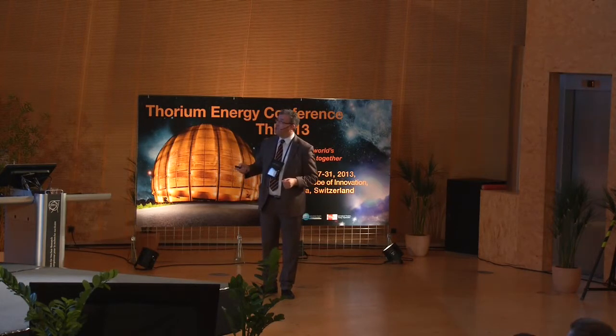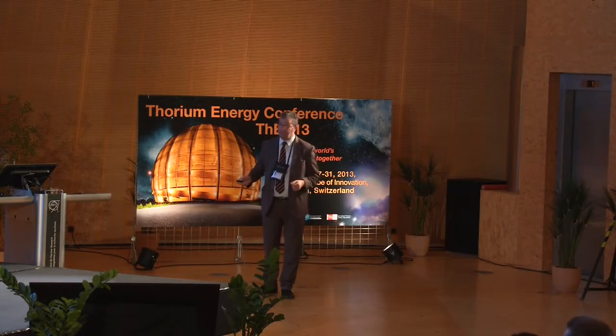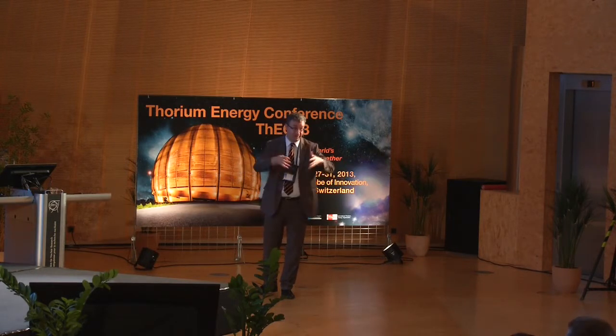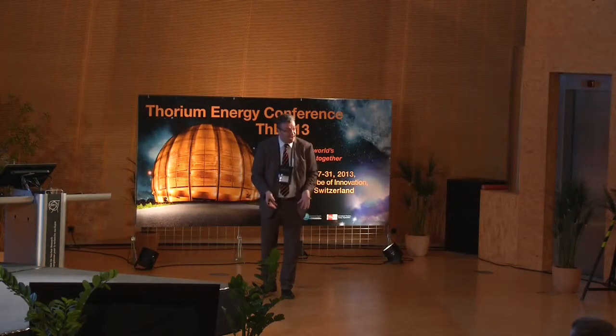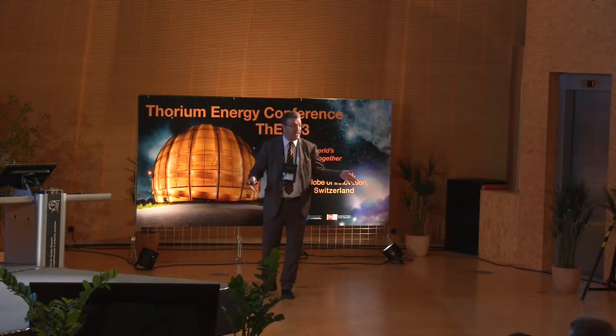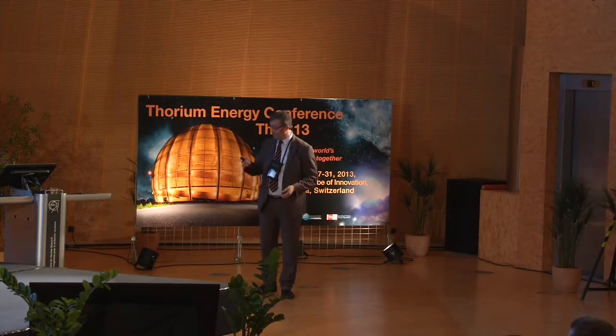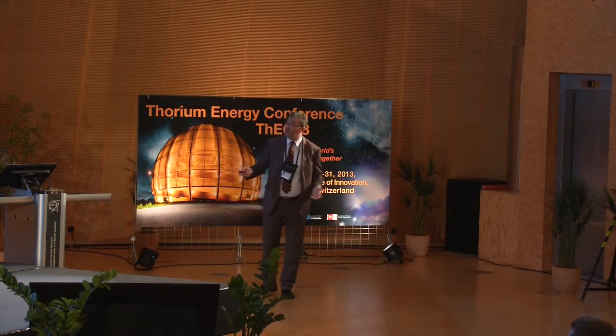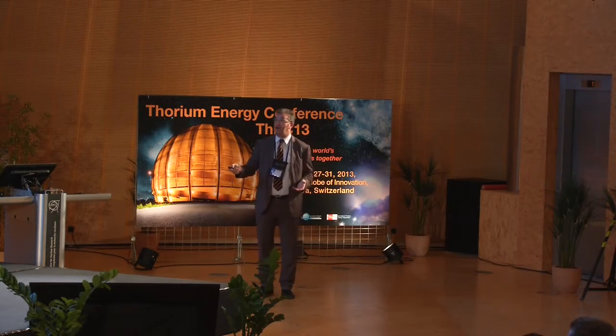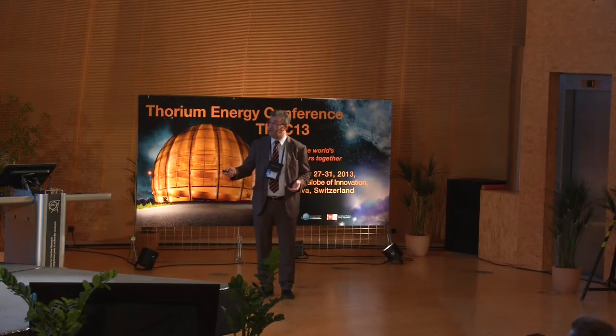We have also a crown of assemblies with yttrium zirconium oxide to act as a reflector. You save fuel if you are reflecting neutrons, and you are protecting the barrel of your fuel, so the DPA is reduced in it. And then this is an experimental machine. We have plenty of experimental positions. These yellow dots, the central one will contain the spallation target, or if we operate in critical, it can become an experimental position. The other ones are experimental positions.